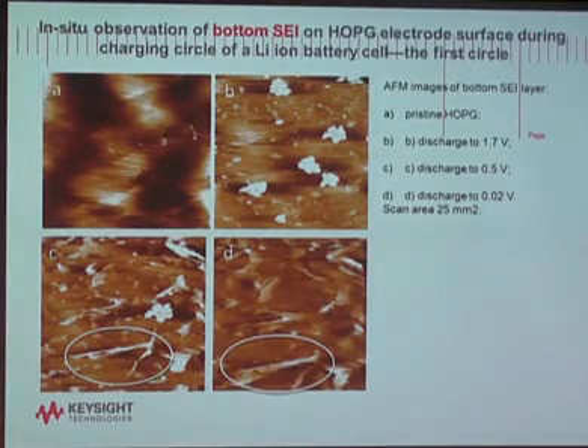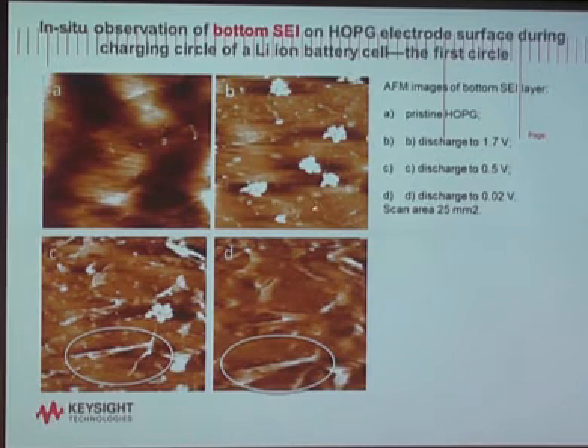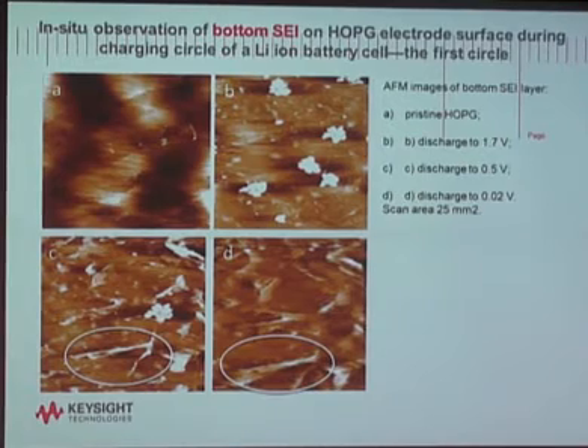Because it delaminated, we could use the AFM tip to remove the first layer and expose the second layer, to see what happened. And we see that the second layer has also had some changes, but its changes are very different. This is pristine HOPG, has some noise. And this is discharge at 1.7 volts. You can see there's a lot of steps that started to increase in thickness. All right, we know that atomic steps have a fixed thickness because it's the size of the interatomic distance of layers of graphite. And why did the distance increase? That's because the lithium ions actually inserted themselves between the two sheets of graphite. That's what we believe.